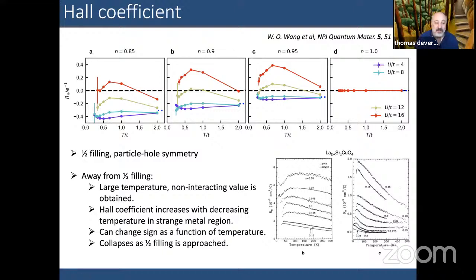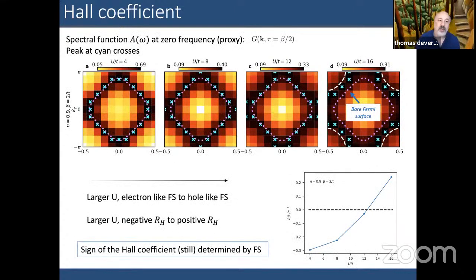So this is not the standard behavior that one sees in Fermi liquids. But you can still try to analyze it the same way by looking at the Fermi surface. So here's a proxy for the Fermi surface. It's the electron's Green function taken at imaginary time beta over 2 in the limit that temperature goes to zero. This is a good mimic for the intensity of the spectral function at the Fermi surface. And so what I'm plotting here is for different values of U of 4, 8, 12, and 16, and one particular doping.